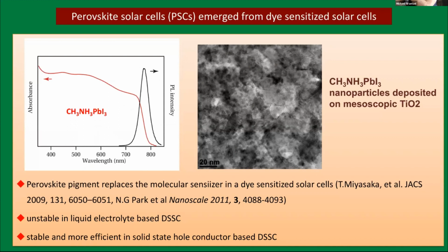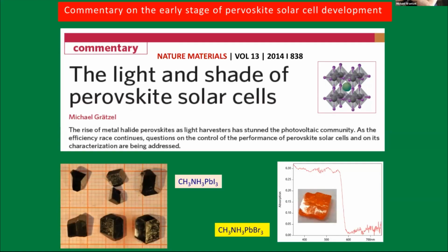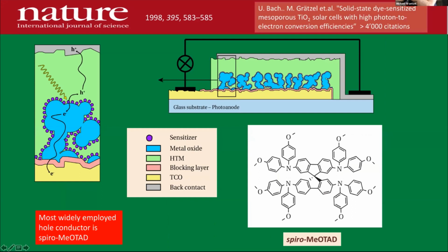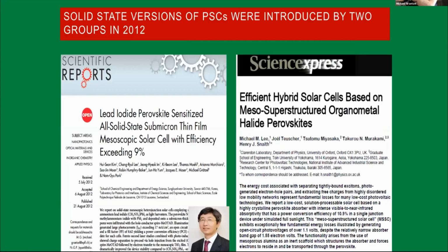And so here is how, at the very beginning, I already mentioned to you that we had the dye-sensitized cells with the perovskite. Here you see the nanoparticles of perovskite, these black dots. That was the very beginning on the same mesoscopic films we had developed for the DSC. And then came the solid state version, and what was used was a configuration that we had published in Nature in 1998. It was a solid state version with spiro, a triarylamine type hole conductor. Otherwise there's the same architecture. The hole conductor replaced the electrolyte, you have a solid state cell. And so that was used to develop the present version of the perovskite solar cell.